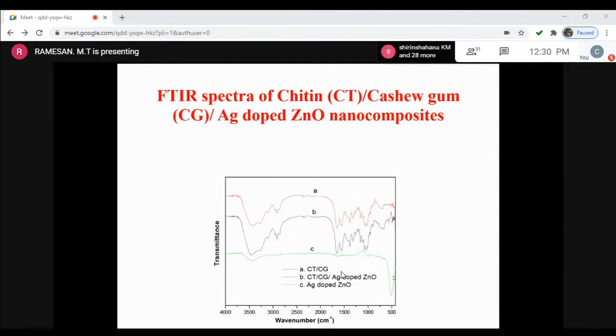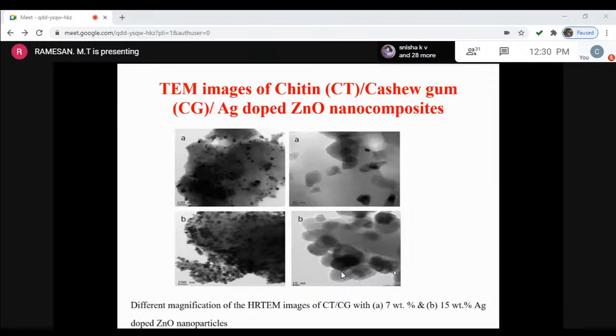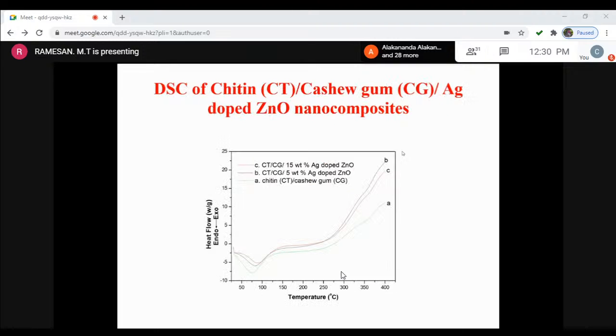The FTIR spectra support the formation of silver doped zinc oxide in cashew gum. This is the XRD pattern, and these are the TEM images that the project student took, and these TEM images also support the formation of zinc oxide nanoparticles in the chitin cashew gum blend system. This is a DSC, and DSC also shows, similar to the earlier work, that the glass transition temperature of the blend increases with increasing loading of nanoparticles, because the more the loading of nanoparticles, the less the movement of the chain. We can say that the rigidity of the system increases, which leads to a higher glass transition temperature.